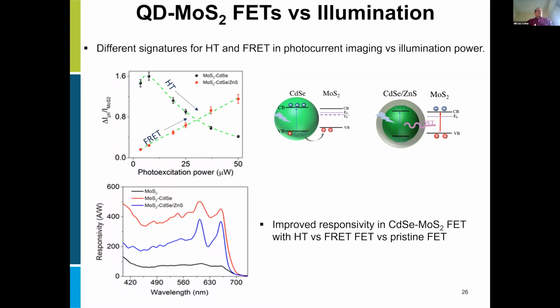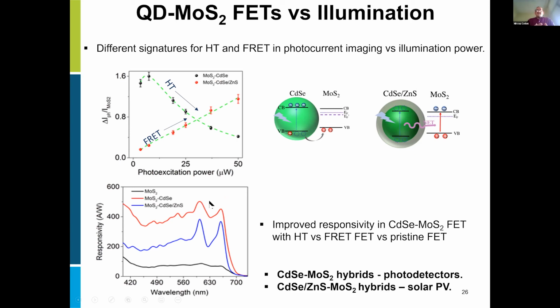Measuring the responsivity, which is nothing else than the optical input versus the electrical output of this device, we observe that devices functioning on core-only quantum dots show the highest sensitivity, which makes sense because they like extremely low light levels here. So they can eventually be used to develop photodetectors, while devices based on core shell quantum dots will produce more charges, or more photocurrent, when they see more light. So we can utilize this kind of hybrids or heterostructures for